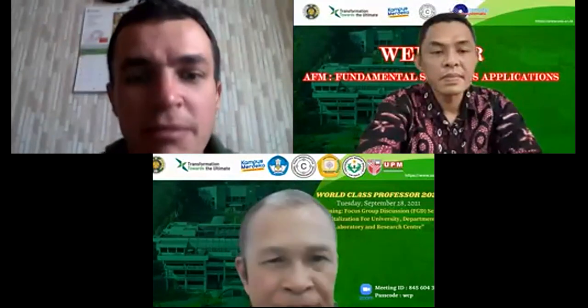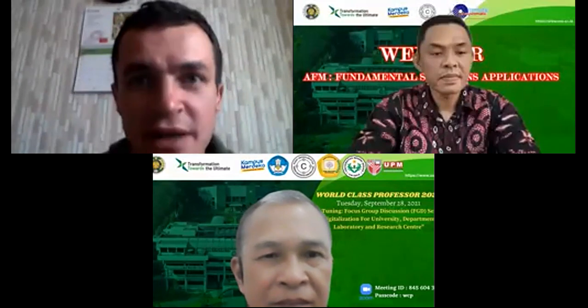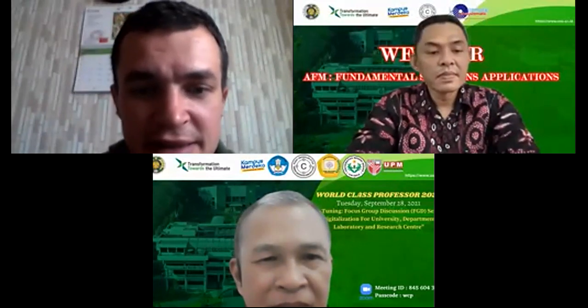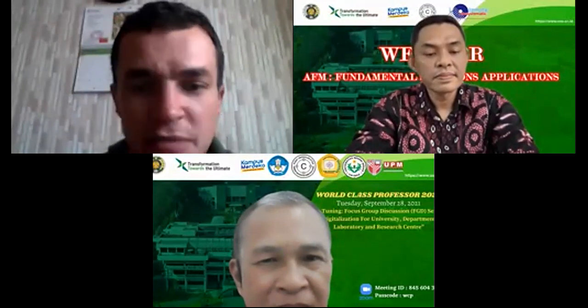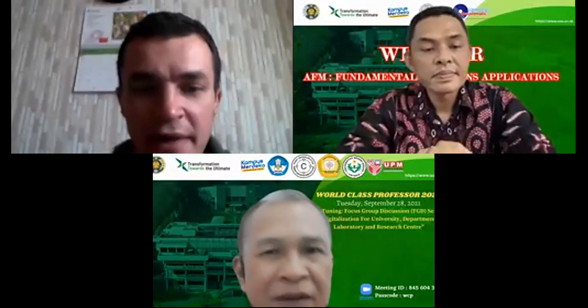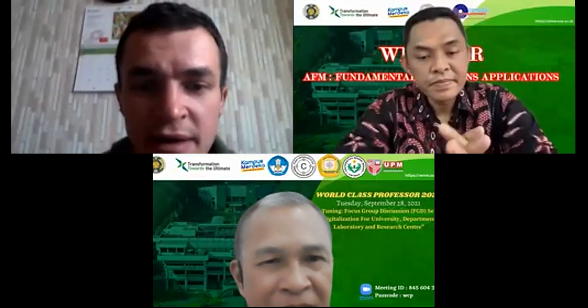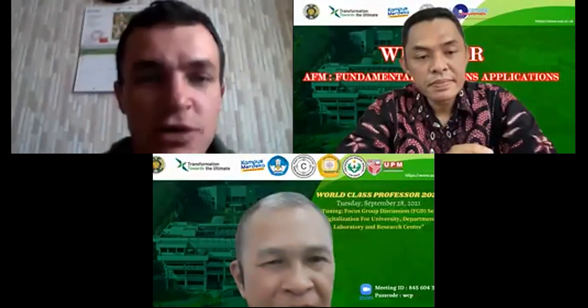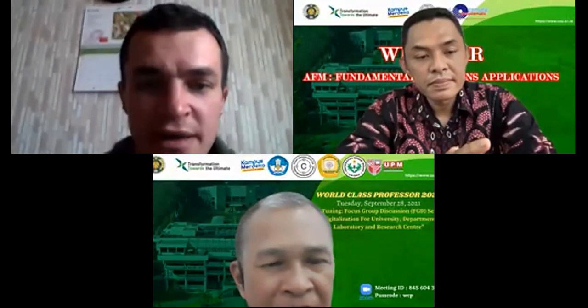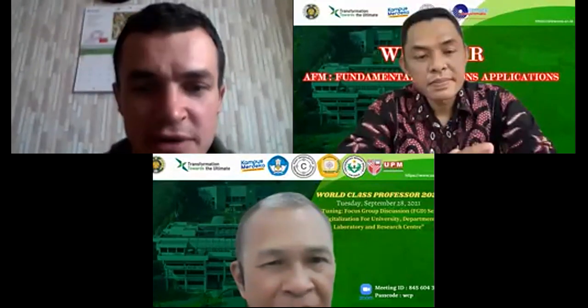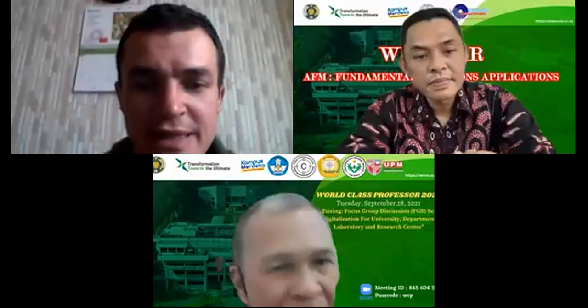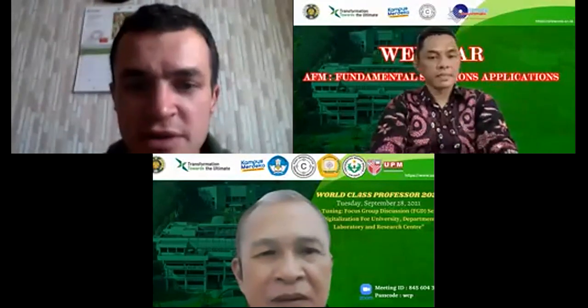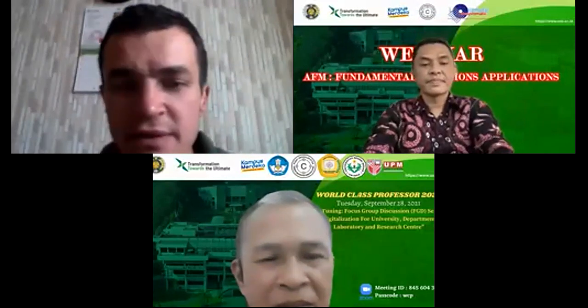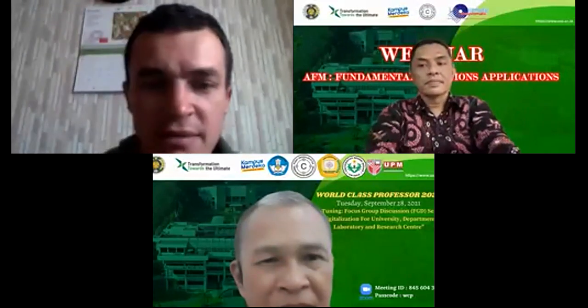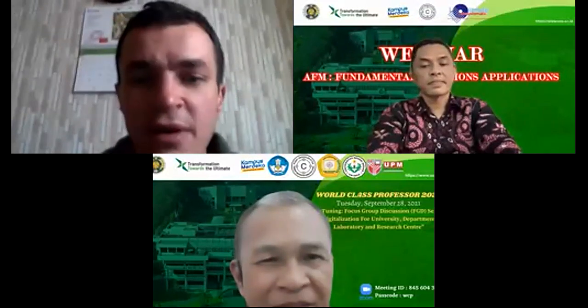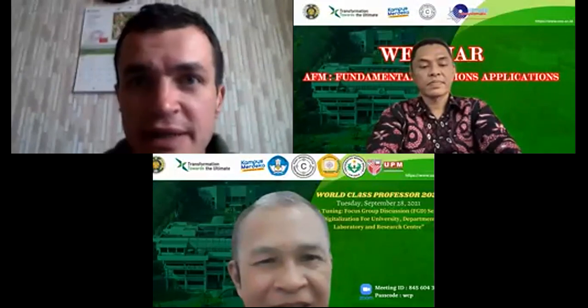So you can get, for example, a 1 micron size with 8,000 points. In that case, the step size between two points in XY will be very small, like 1 nanometer or a few nanometers. This scanner is controlled by the electronics, and the DAC converter applies some volts to move the scanner in X and Y. It slowly moves from left to right, then one step in Y, then again one step in Y, and we get such a morphology relief for each line.